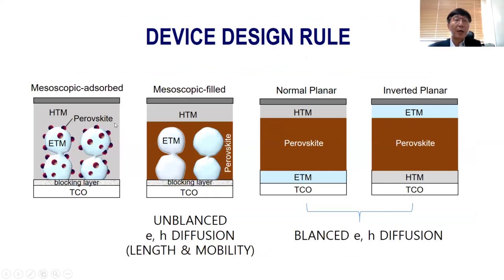We have 4 different kinds of devices for perovskite solar cell. One is the mesoscopic n-i-p perovskite structure. This is the first version. And the next version was the mesoscopic filled perovskite solar cell. And then recently, people frequently use the normal planar structure or inverted planar structure. However, in that case, you have to consider the electron hole diffusion length and mobility. If this is unbalanced, then probably the mesoscopic filled structure is better. For the case of balanced electron hole diffusion length, then the planar structure is pretty suitable.